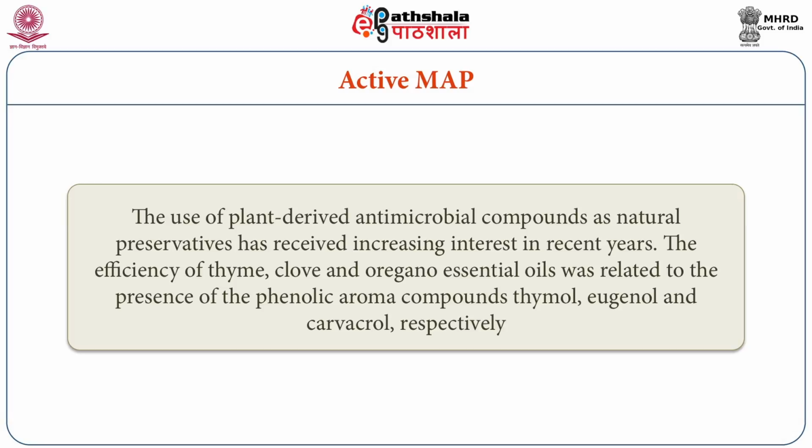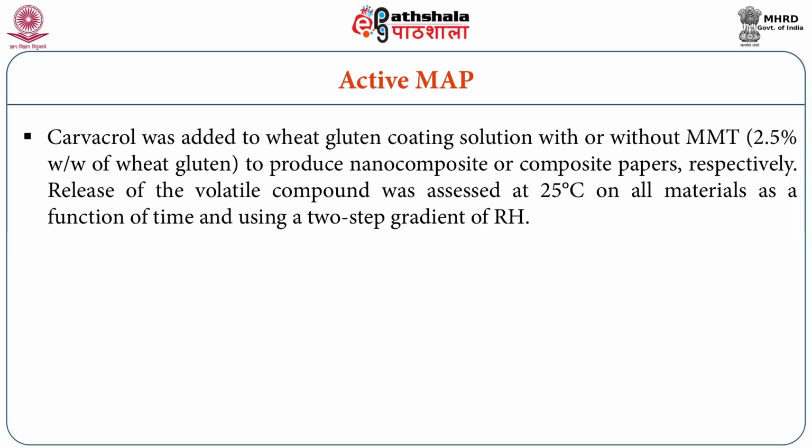The efficiency of thyme, clove and oregano essential oils was related to the presence of phenolic aroma compounds thymol, eugenol, and carvacrol respectively. Carvacrol was added to wheat gluten coating solution with or without MMT to produce nanocomposite or composite papers respectively.